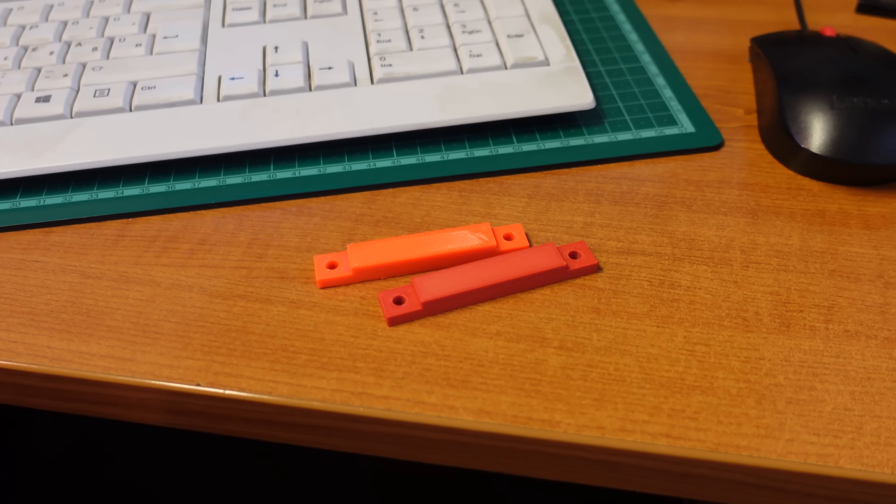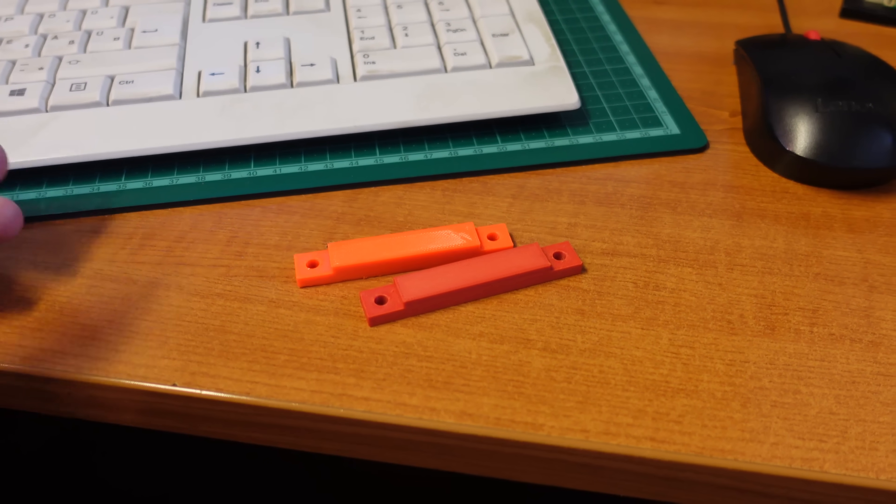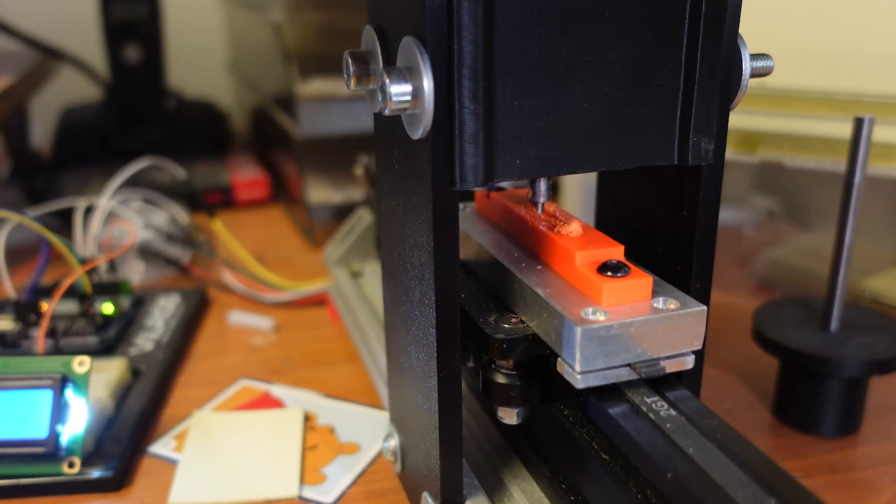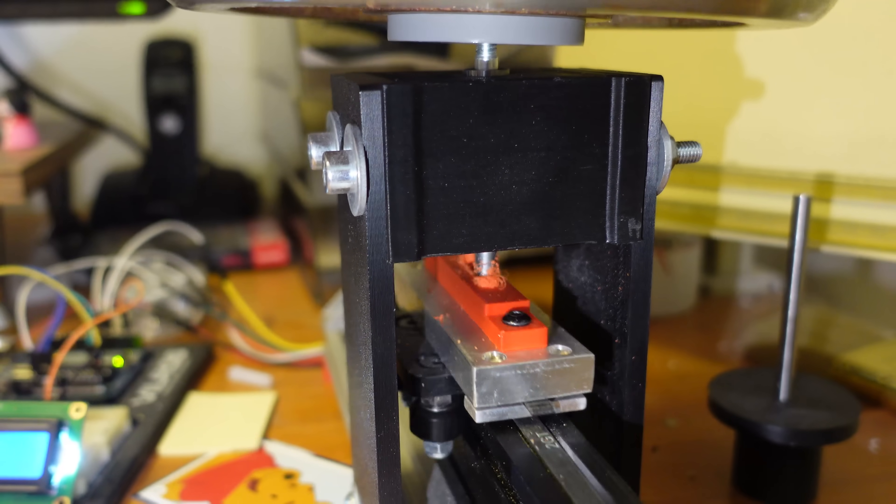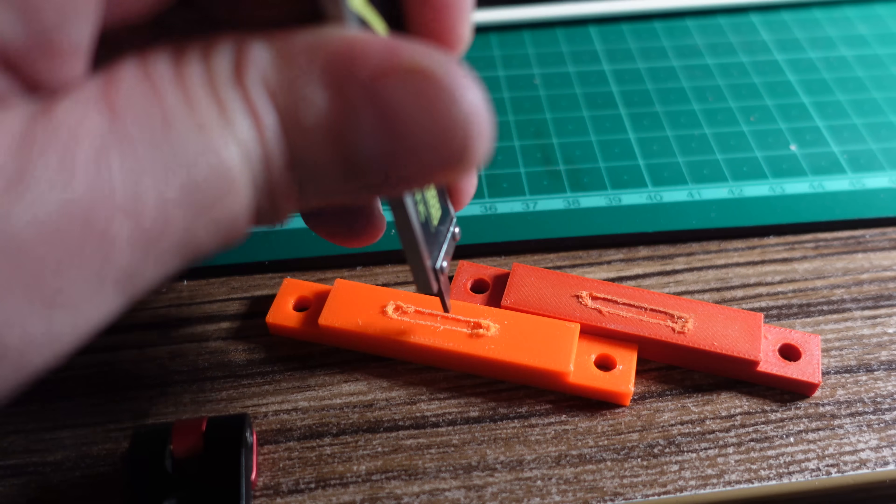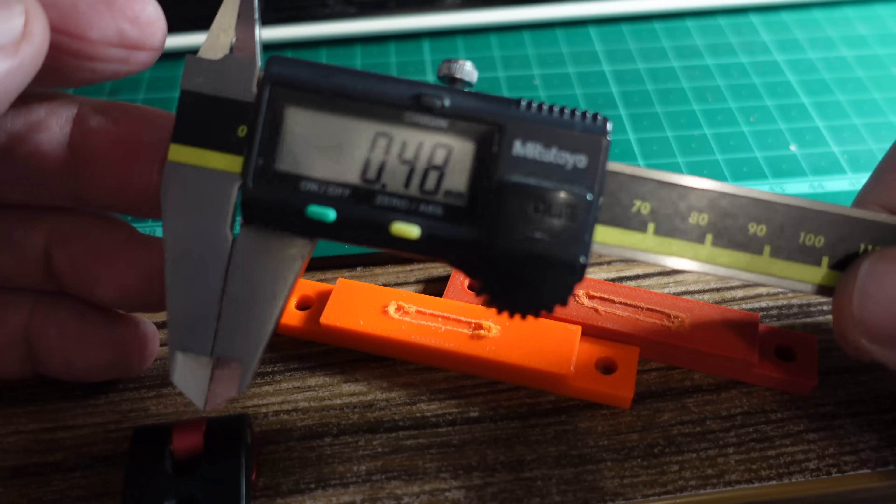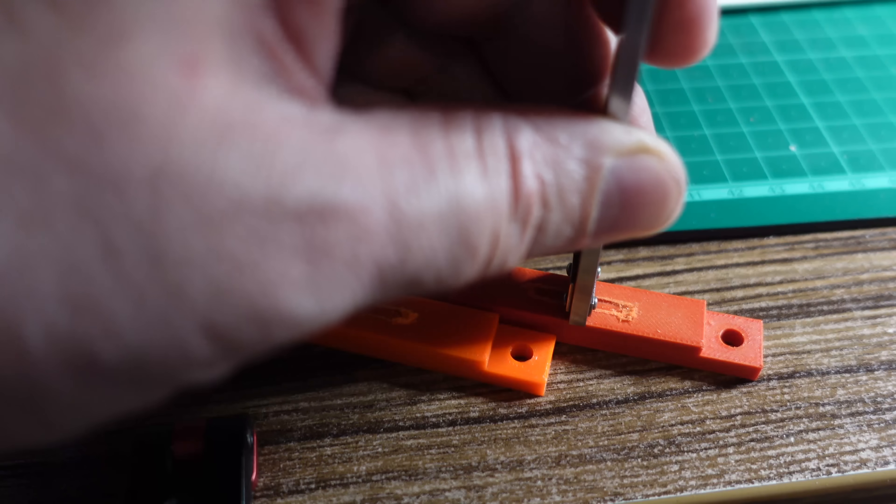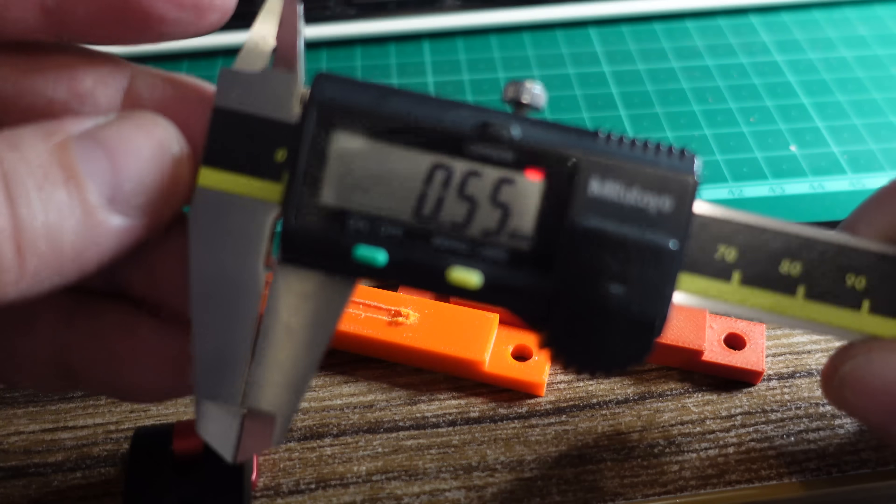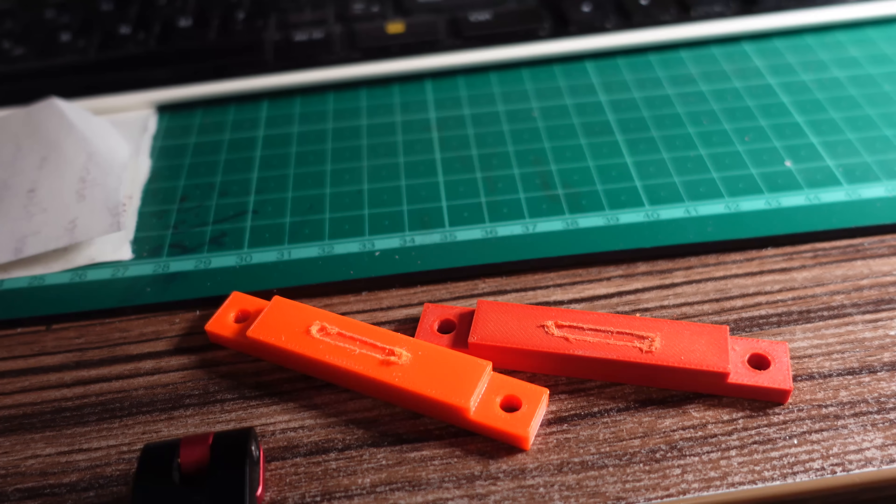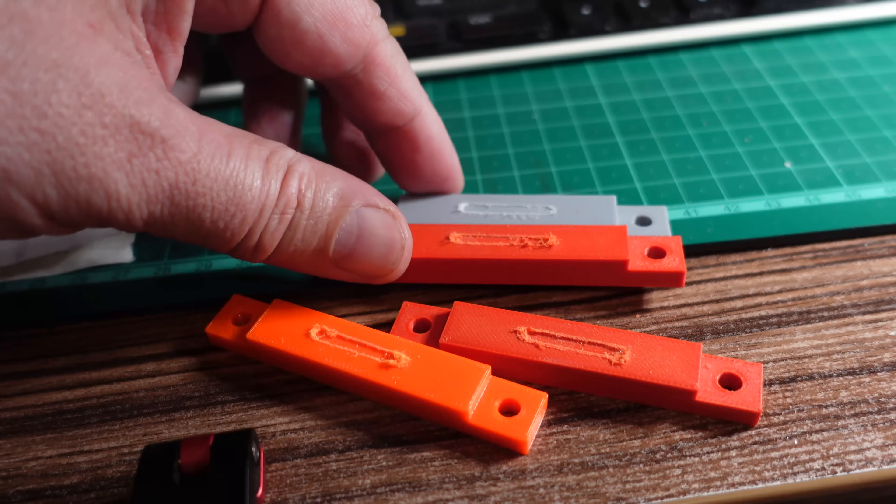Definitely something I want to check, so I will do this test again but this time with 200 repeats, and I will compare it with the Proto PETG. This is Proto PETG, and this is the Spectrum. I cleaned the edges a little bit. Now let's measure the depth. 0.48mm. 0.55. Interesting, again bigger wear on the Teflon version. And these are from the previous measuring.